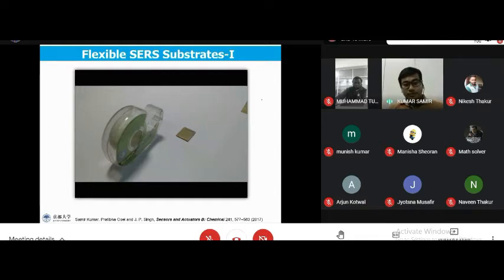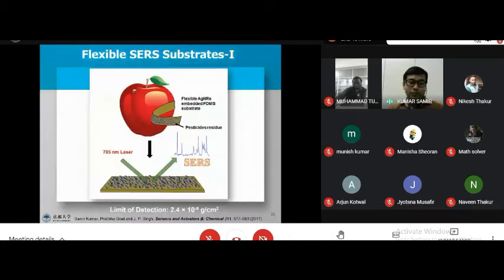Actually, so this is our substrate. What we did, we took this scotch tape and put it on our substrate and we peeled it, and there was no peeling of the substrate even from using this scotch tape. So it's a very robust substrate, and the second advantage is that it is flexible, so you can put it or apply it on a surface and then you can collect the data.